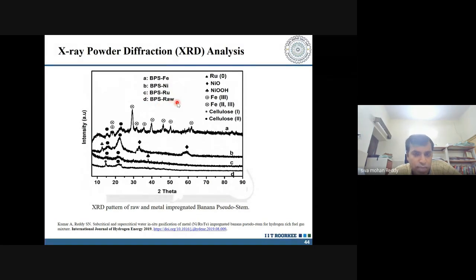Okay, so this is a typical XRD profile of the raw and impregnated biomass with different metals like nickel, ruthenium and iron. You see the sharp peaks between 10 to 25 degrees of your 2 theta values. They correspond to the crystalline forms of cellulose, which exist in cellulose 1 and cellulose 2 forms. Okay, and you have nickel oxides present, with peaks represented over here.